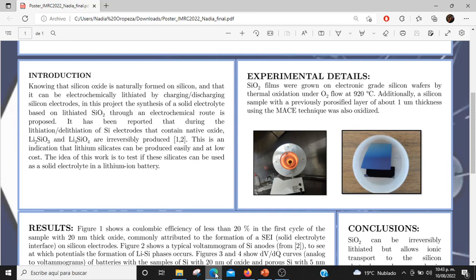The silicon oxide films were grown on electronic-grade silicon wafers by thermal oxidation under oxygen flow at 920 Celsius degrees. The thickness of the films were 20 nanometers and 5 nanometers. Additionally, a silicon sample with a porous layer of about 1 micrometer thickness, made using the metal-assisted chemical etching technique, was also oxidized. Etching was performed in two steps.